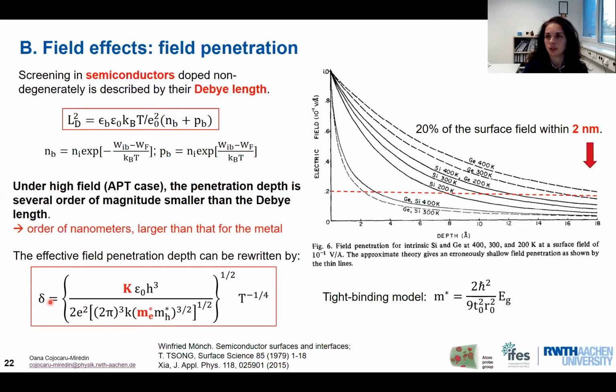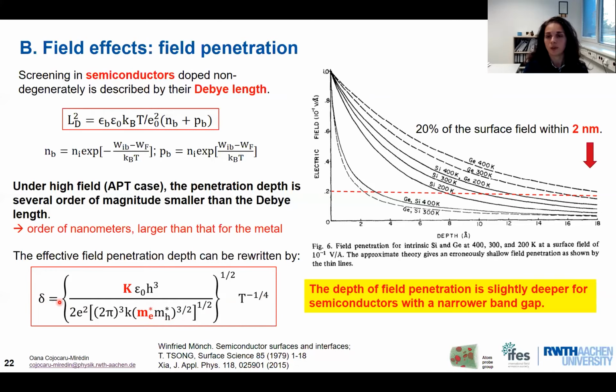And this really nicely shows that the depth of field penetration is slightly deeper for semiconductors with a narrow band gap. And if we want some quantitative numbers, I have found in the literature work where they have shown the field penetration depth for silicon and germanium. Of course, they are not narrow band gap semiconductor materials, with a band gap of about 1.1 electron volt for silicon. But although they have a pretty moderate band gap, we have a pretty high field penetration depth of about 2 nanometers.